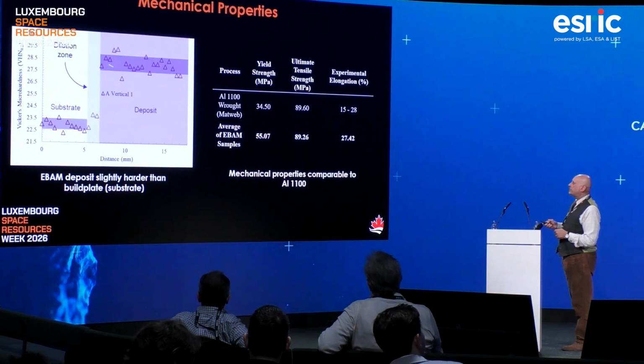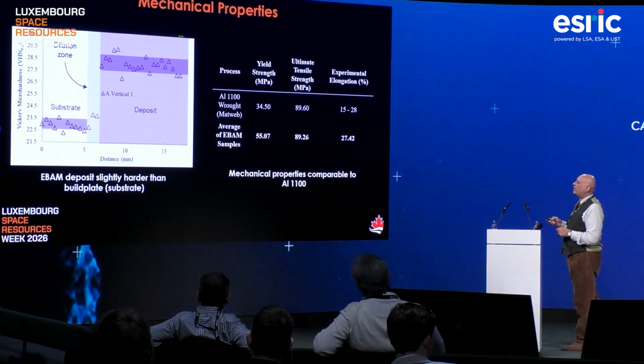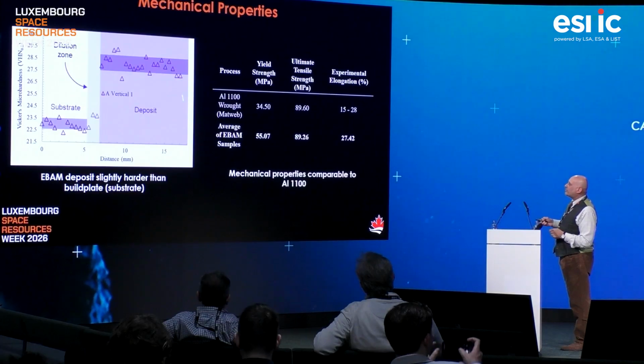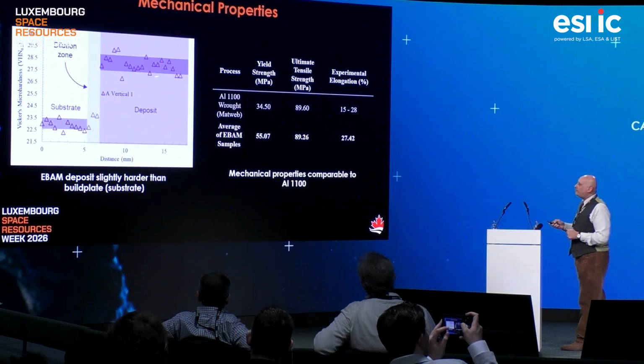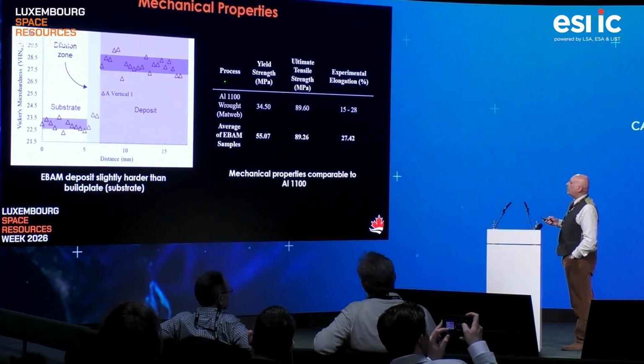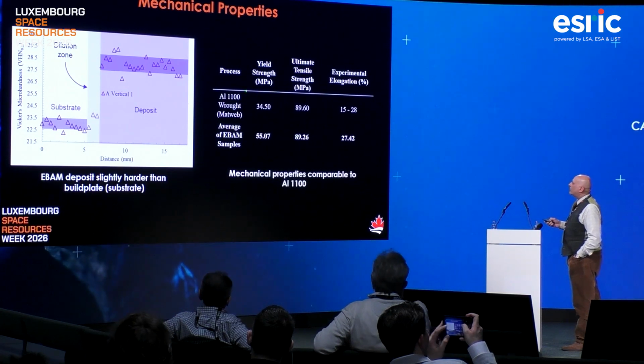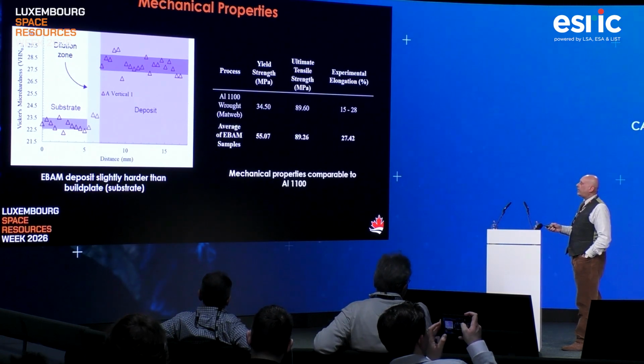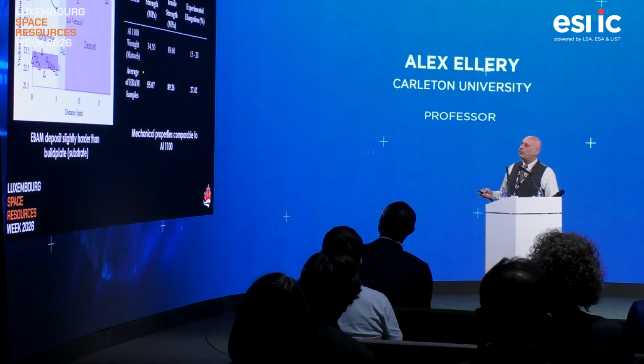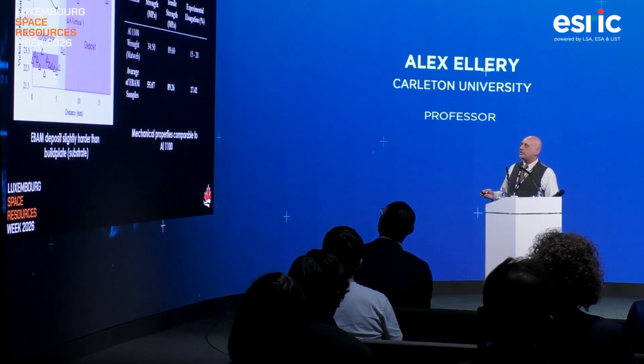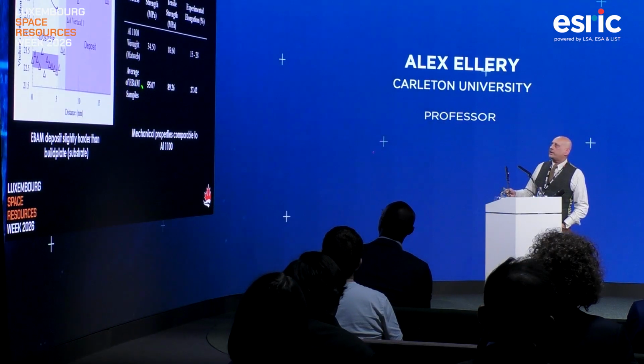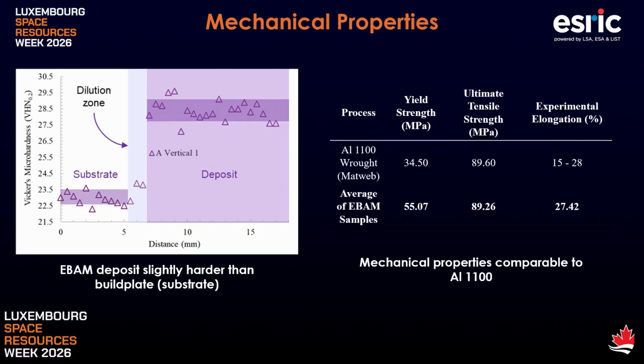So Javier carried on doing some testing. He did explain this to me, but I don't think I was listening. Apparently, if you compare the off-the-shelf aluminium 1100 series with what we deposited, you'll see that the yield strength of our deposit is higher than the commercial off-the-shelf. All the other parameters were almost identical. So we're getting very good results in terms of the mechanical properties.